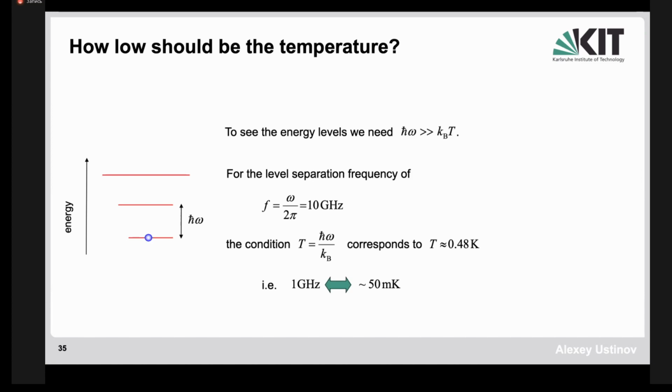That explains why aluminum is the material of choice, simply because you don't need any high temperature superconductor. You don't need niobium. Aluminum itself, which has a gap of about 1.2 Kelvin, will be an excellent superconductor at 50 millikelvin, because most of the electron excitations will be frozen there. Most of the particles will be frozen. In reality, it's different, but that's the expectation.